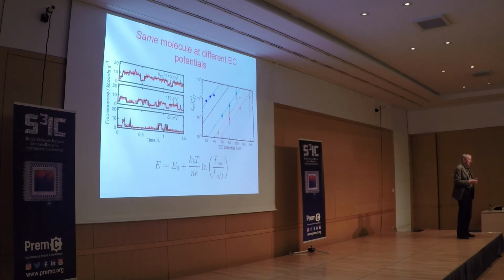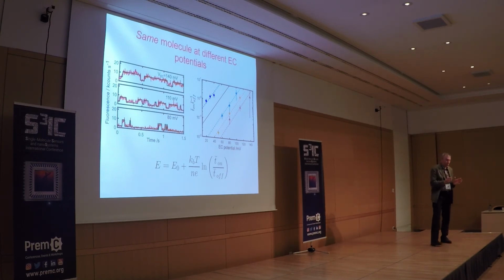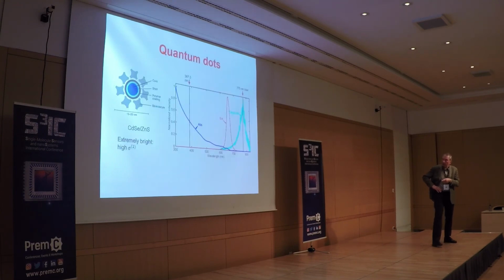Thanks for this inspiring talk. My question is, how did you avoid quenching of the quantum dots by the gold nanorods, but you observed this enhancement? All right. So the question is about quenching of luminescence of the quantum dot by the rod. First of all, the quantum dot is not exactly in contact with the gold, right? There is this functionalization layer that is schematized here. This is a few nanometers. It already creates a distance between the rod and the gold and the core of the quantum dot, which is the emitting part.